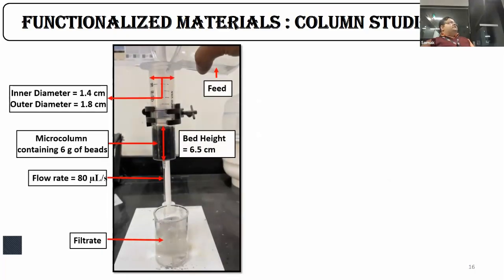We used a microcolumn with a bed height of around 6.5 centimeters, and we used the gravitational method because in most cases, if energy is not utilized, we wanted to see what effect that has on carrying out the studies. If you use energy or pressure, you can get full bed utilization. But in the gravitational method, there is no energy utilization taking place, and full bed utilization does not occur because of the shortest path taken by the water stream.